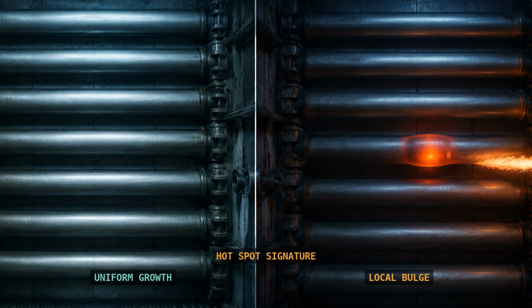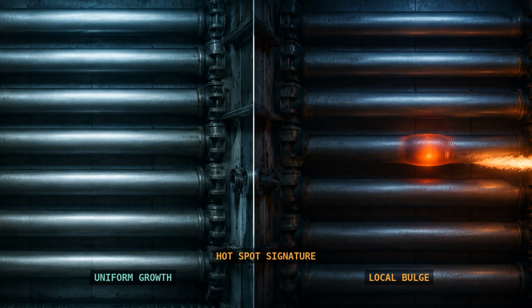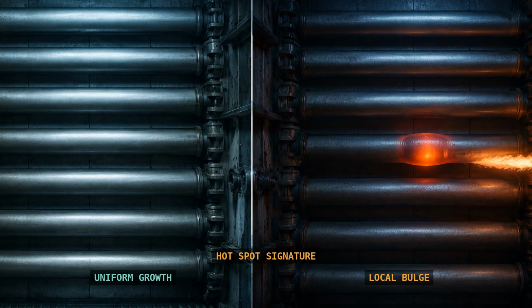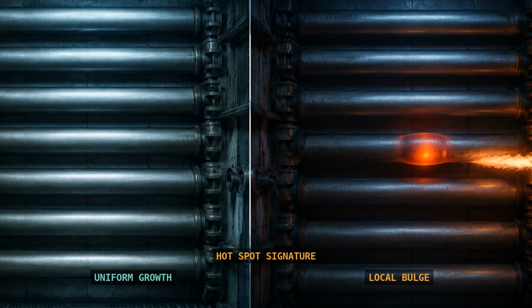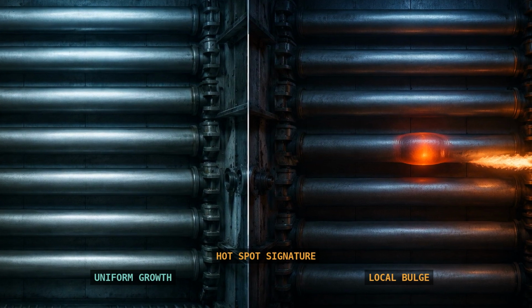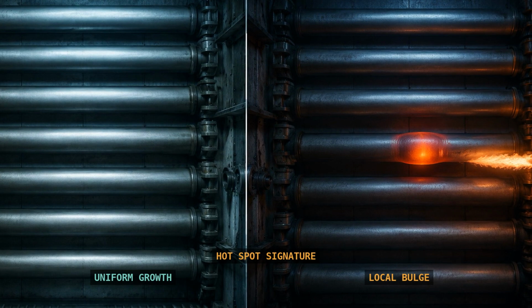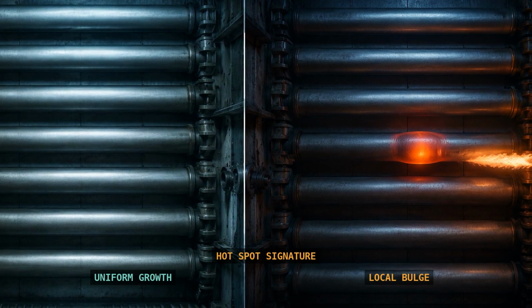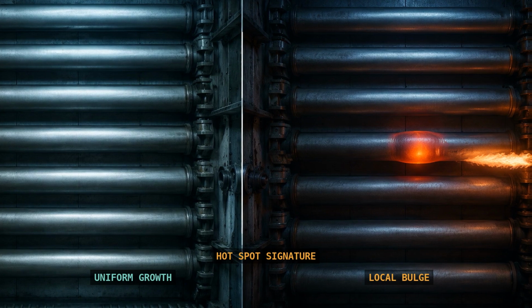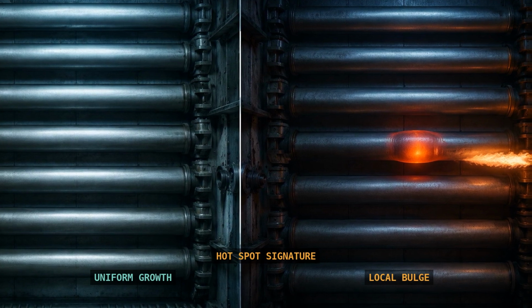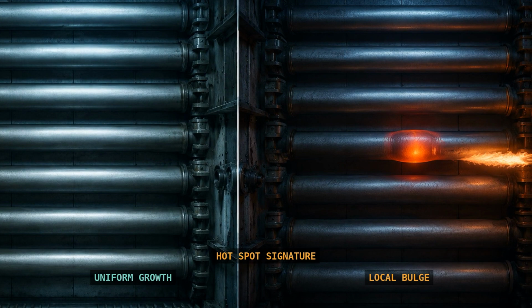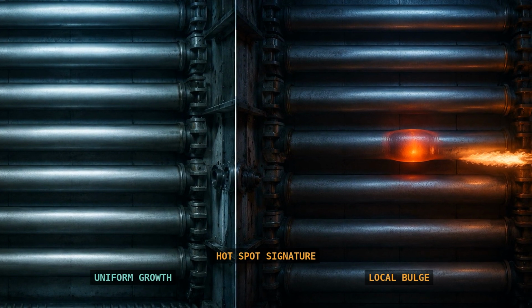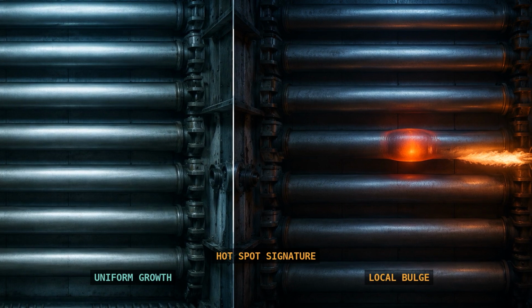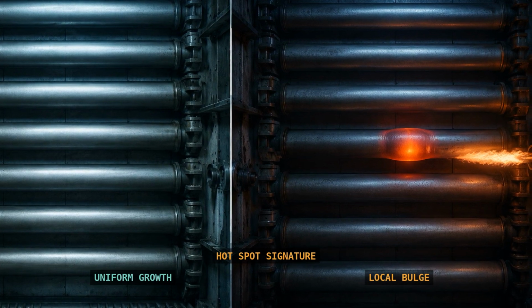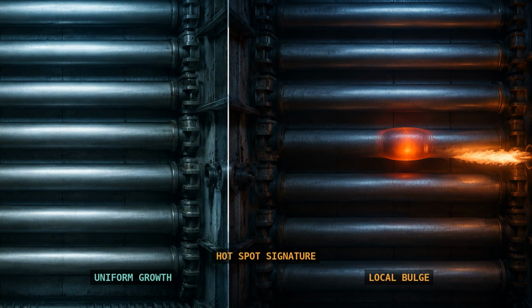This is why a local bulge gets an engineer's full attention. It says the metal right there is entering tertiary creep, the accelerating endgame. The bulge's shoulders concentrate stress. The wall beneath it is thinner, and the grain boundary voids and microcracks are concentrated exactly there. When creep tubes fail in service, it's typically an axial split right at the hot bulged location, sudden, into a firebox full of ignition sources.